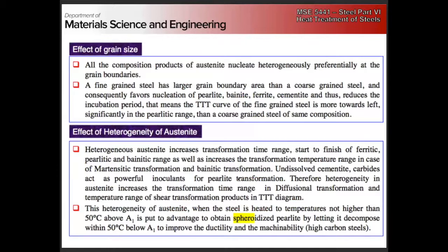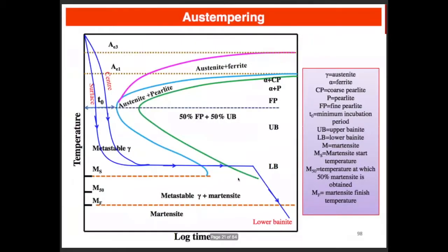But the key thing is that the effect of having a heterogeneous structure doesn't necessarily shift the whole curve over. It spreads it out, right? So you'll be starting earlier but taking longer to finish, for the same mean grain size as if you had a homogeneous, small, tight, standard log normal grain size distribution, right? It's kind of a minor point, but